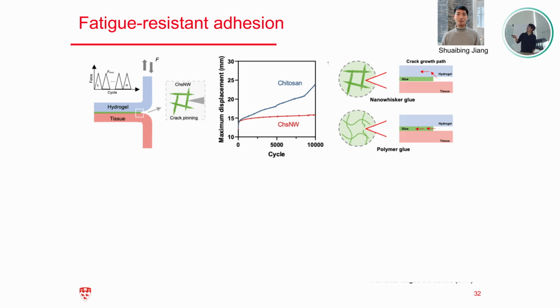So on this slide, I want to get your attention on this new test called the cyclic fatigue test. What I showed you before, all those adhesion energies, is essentially a one-time loading. You peel it off, right? But in that case, you get a high level of adhesion energy. But in practice, this material may be subject to cyclic loading. As you may know, for a lot of engineered materials, it has very high strength, but under cyclic loading, it can easily rupture and fail at a much lower loading, lower force. The reason for that is this material suffers from the fatigue factor. That is the case for this hydrogel polymer case.